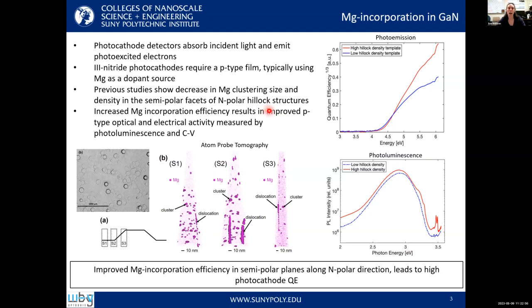Previously, we've shown that photocathode structures grown on nitrogen polar GaN templates with a high density of these hexagonal hillock features result in a very high quantum efficiency for the photocathode devices compared to a sample that had very few of these hillock structures. And we found by using atom probe tomography that the magnesium dopants incorporate more efficiently within the semipolar facets of these hexagonal hillock structures, leading to more uniform magnesium distribution and thus improved optical and electrical properties of the film.